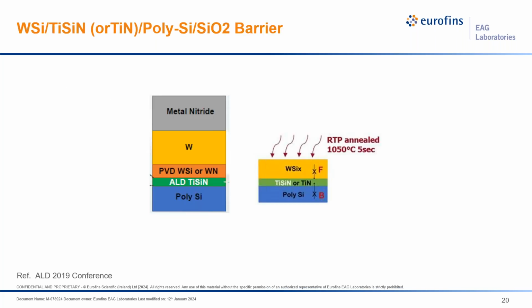So let me just show one particular example. In this case, we are looking at a metal nitride metal stack with a barrier layer of some sort of titanium silicon nitride, and then some polysilicon with a boron doping. This sample was annealed, and they wanted to look for a cross diffusion of the fluorine that was present in the tungsten silicide, as well as the boron that was present in the polysilicon, whether or not they intermix.